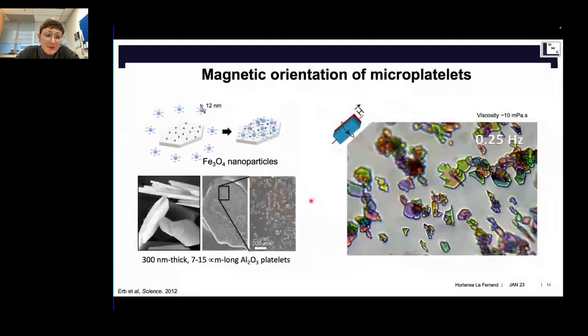So how does it work? Now I share with you a little bit more detail. This is a method that was developed not by me, but by someone else in 2012, so 10 years ago. And the principle is fairly simple. You take small microplatelets, typically 10 micrometers in diameter. Here the example is aluminum oxide microplatelets. You put them in water and you add iron oxide nanoparticles, with the opposite electrical charge, so that they adsorb electrostatically at the surface. Okay, so you make this new microplatelet that is responsive to magnetic field.